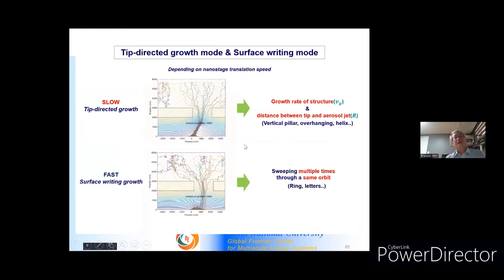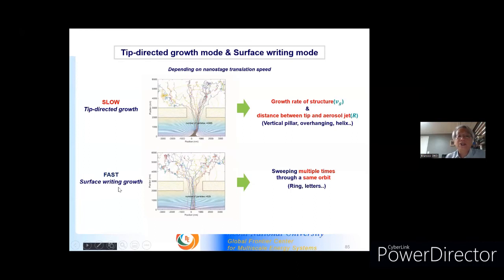Our technique actually has two different modes. Tip-directed growth mode, which I just showed you, has particles deposit on the top of the growing structure. But if you move this mask too fast, particles do not deposit on the top of the growing structure, they deposit just on the surface. This is the surface writing mode.